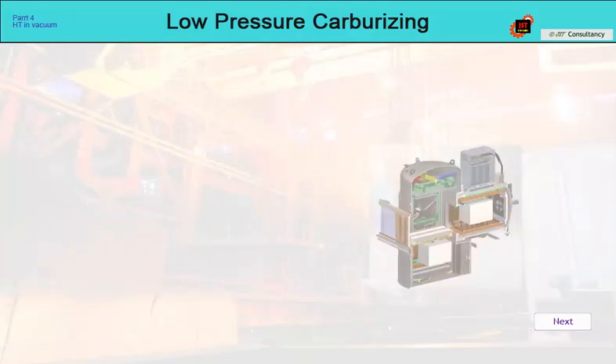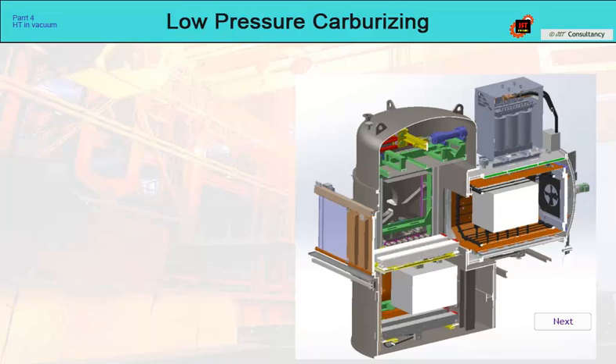But not only gases and their control have an effect on the formation of soot in the hot zone. Another problem is the physical contamination of the chamber with hydrocarbon vapors from the quenching oil. These two phenomena often add up and together cause the formation of sticky carbon condensates, so-called tar, soot, polymerized carbon, on the wall's heating elements and diffusers.